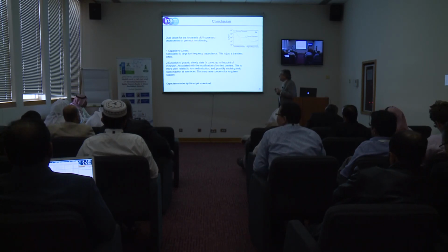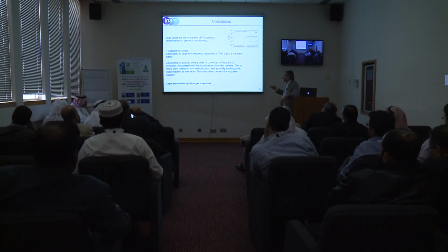So I have one conclusion. I think this clarifies a lot of the hysteresis and summarizes many results observed in the literature. So there are two causes for hysteresis. They point to important phenomena. One is capacitive current, which is associated to very large low-frequency capacitance. This is a transient effect, and it's irrelevant for the solar cell operation, which is steady-state operation. And second, there is an evolution of the pseudo-steady-state curve, and this is not irrelevant, because something is happening to the perovskite solar cell with time that is modifying the contacts.